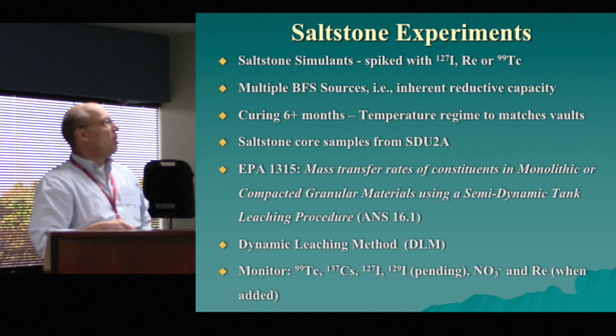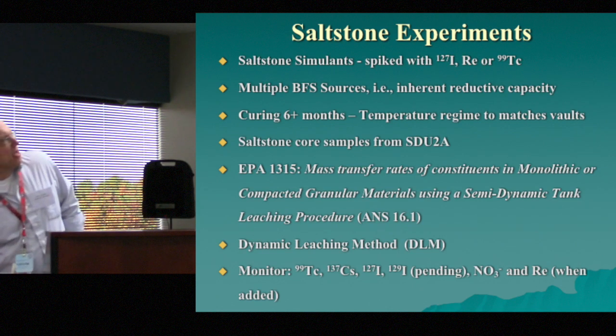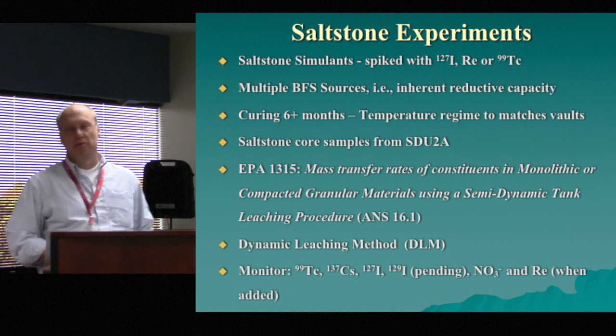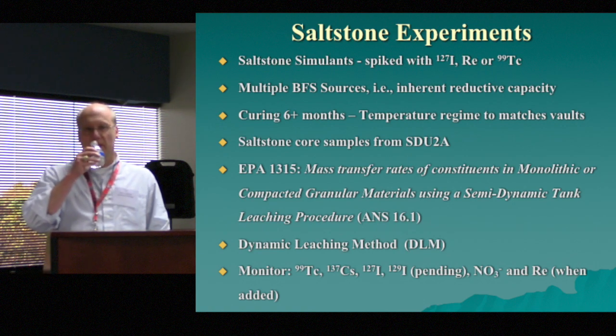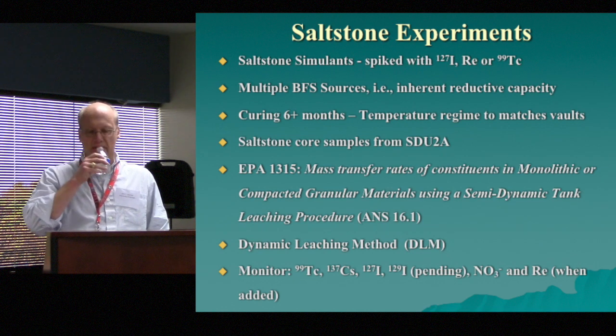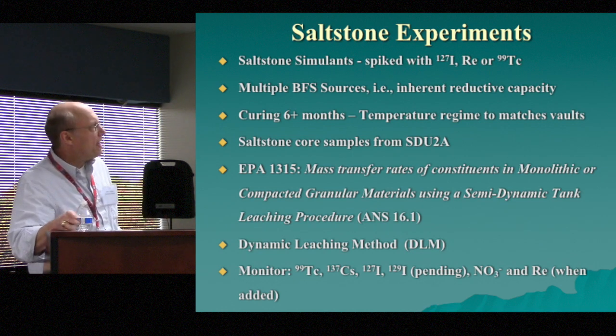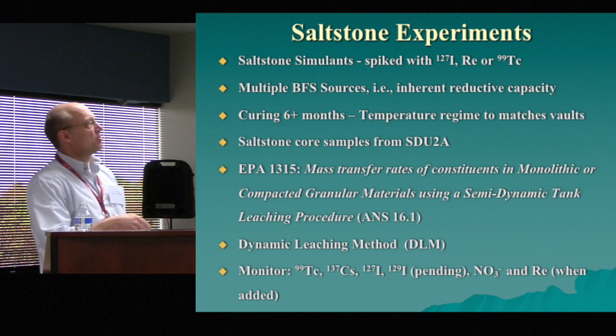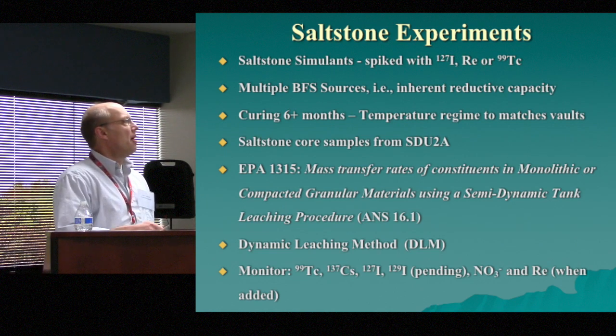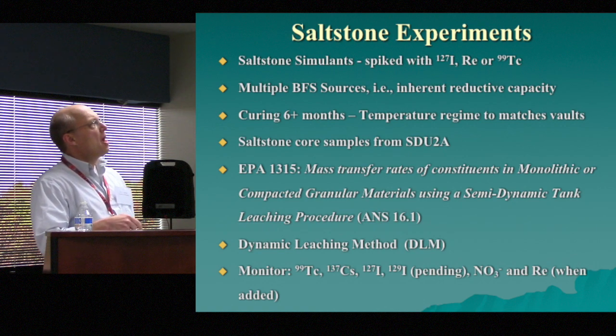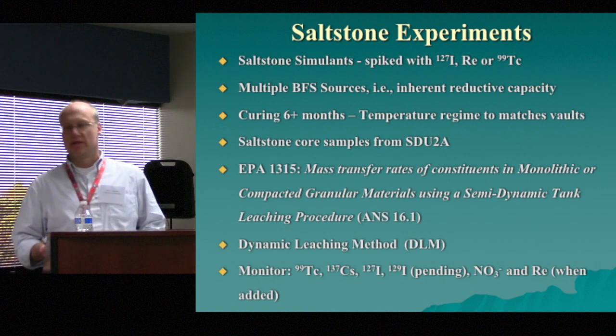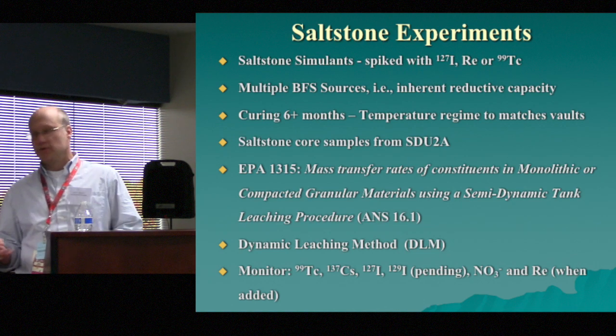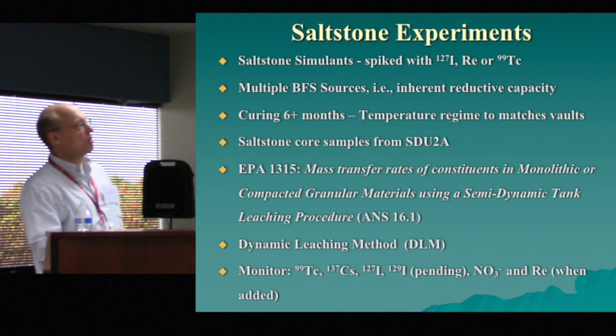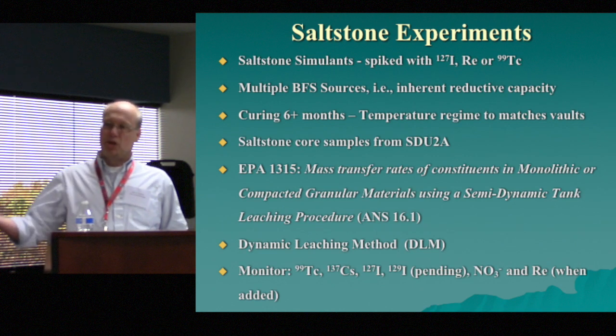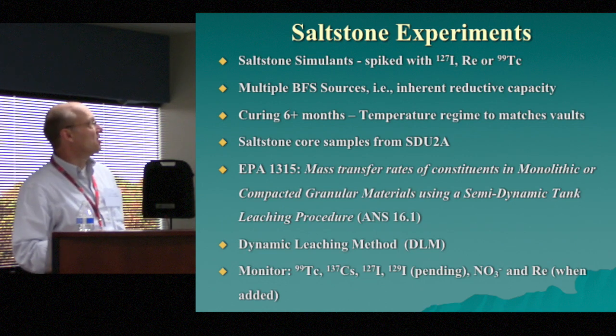We looked at multiple blast furnace slag sources because that is where the inherent reduction capacity comes from that we're relying on to immobilize the technetium. We're curing, actually we'll show some data on some samples that were only cured 3 months, but we're curing much longer times than a lot of times people do in these kinds of experiments. And the other thing that we're doing that they don't do quite often is we're trying to match the temperature regime and the humidity regime within the vaults that Steve talked about.